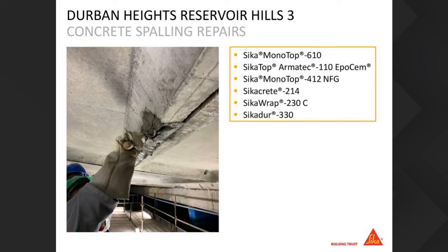So, the products that we used for concrete spalling. Now, there was 15% of surface area that had to be repaired. And the selection of the correct products was critical due to the access that Smart Civils had. So the products that we chose were Sika Monotop 610, which is a polymer modified bonding agent and anti-corrosive coating for reinforcing steel, and SikaTop Armatec-110 EpoCem, also a bonding agent and anti-corrosive coating for reinforcing steel with a corrosion inhibitor. All the rebar that was exposed, grit blasted and cleaned, was coated with 2 coats of Armatec.